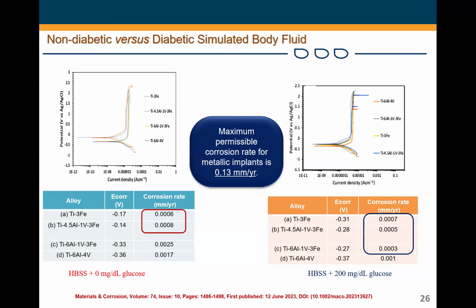So we simulated diabetic and non-diabetic solution. And this was really inspired by the fact that my father is diabetic, and I would like to see, if he's got a broken hip and we have to maybe give him an implant, if my alloys would be friendly in his body. And you see in all situations, when you replace all the vanadium or you do partial substitution, the corrosion resistance of the alloys is more or less the same, and they are way lower, at least 100 times lower than what has been benchmarked as the maximum permissible corrosion rate for metallic implants.